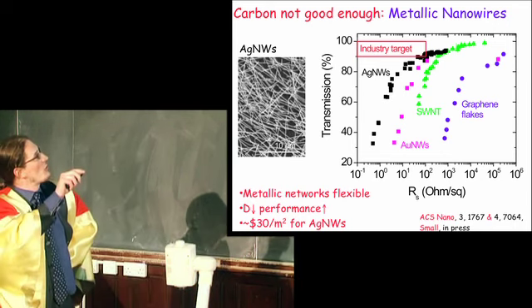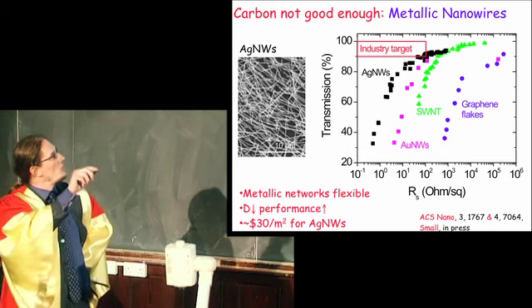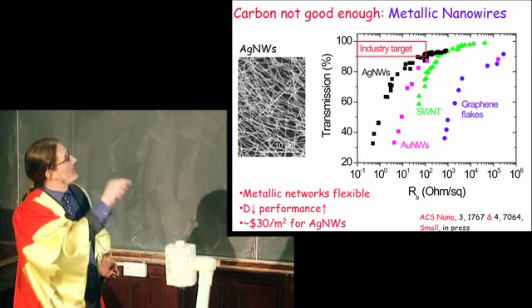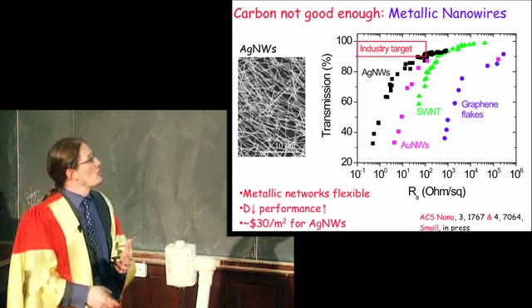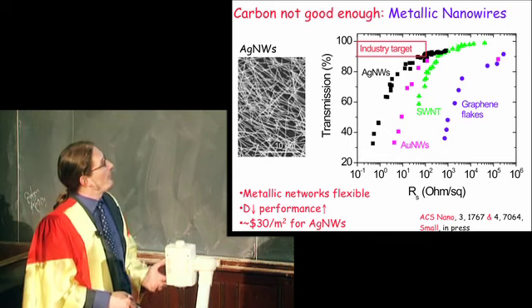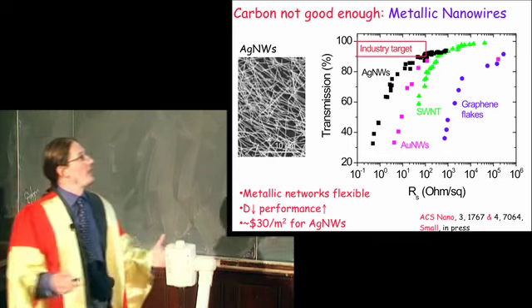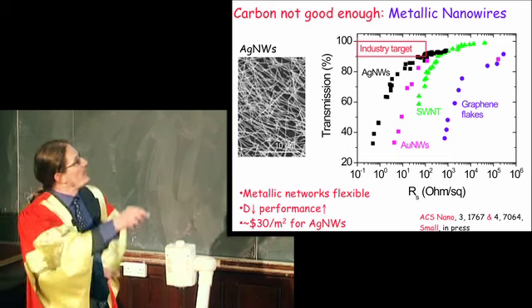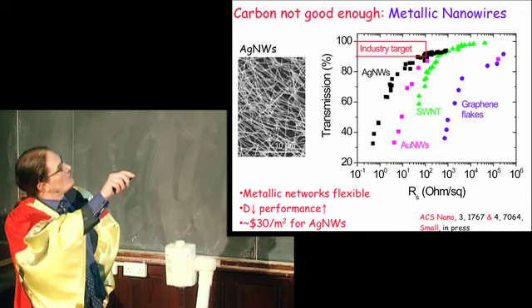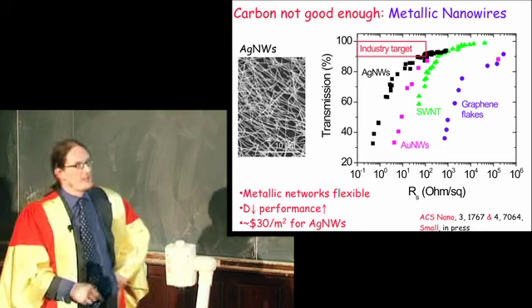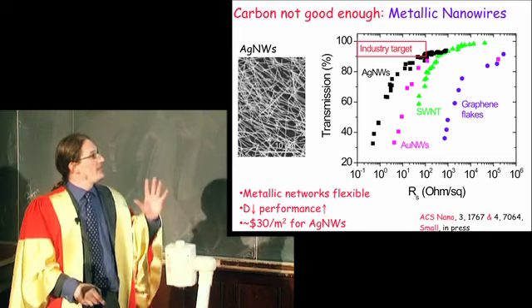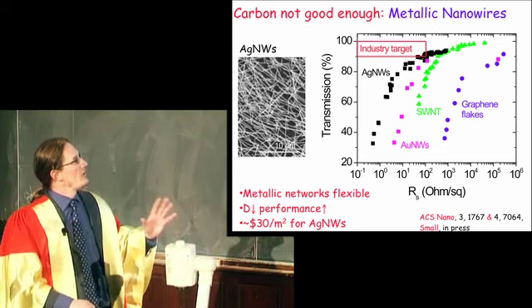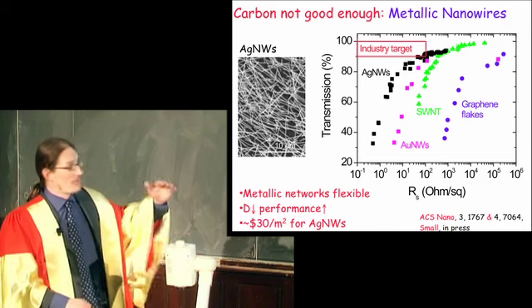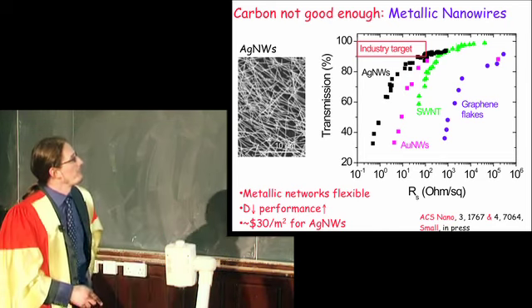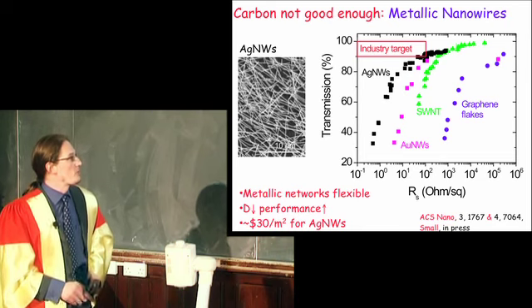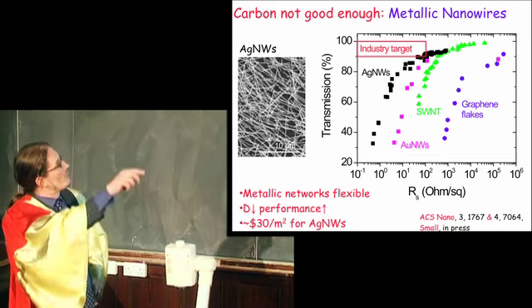Metallic nanowires. You can buy little nanowires that are a few micrometers long, made of metals, in this case silver. And you can deposit by spraying, which is a large area processing technique, networks of silver nanowires that are just the right thickness, just get you what industry want. And this, after 4 years, took us to the pinnacle, the state of the art in this area. And we're one of only maybe 3 groups in the world that can achieve these sort of results.